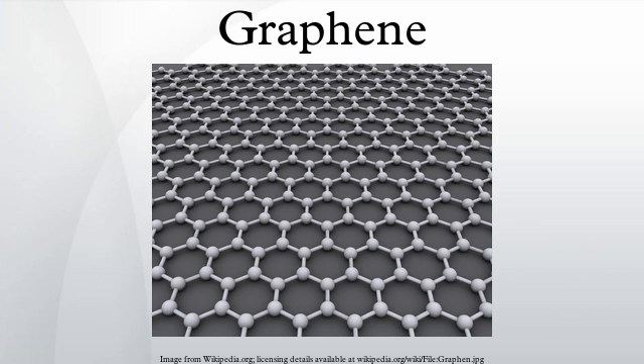Strong magnetic fields. Graphene's quantum Hall effect in magnetic fields above 10 teslas or so reveals additional interesting features. Additional plateaus of the Hall conductivity are observed. Also, the observation of a plateau in the fractional quantum Hall effect was reported. These observations would indicate that the fourfold degeneracy of the Landau energy levels is partially or completely lifted.